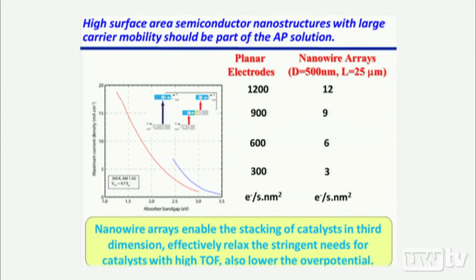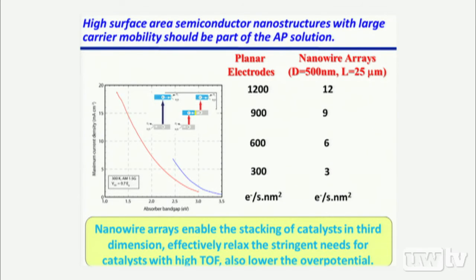Now, with this slide, I want to illustrate the importance of the surface area. Of course, using nanowires, we have the advantage of high charge mobility that's already demonstrated in our solar cell device. But more importantly for solar fuel generation, high surface area, because we need to run basic catalysis for water reduction and water oxidation. So surface area is very important. Imagine we are extracting just 10 milliamps per square centimeter from the semiconductor. That means roughly, if you are dealing with planar electrodes, you are sending 600 electrons every second over 1 nanometer square, if you are dealing with a thin film or single crystalline version of the electrode. And that basically dictates the turnover frequency of the catalyst.